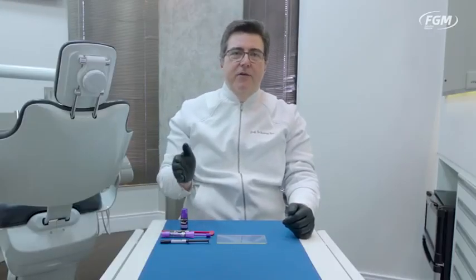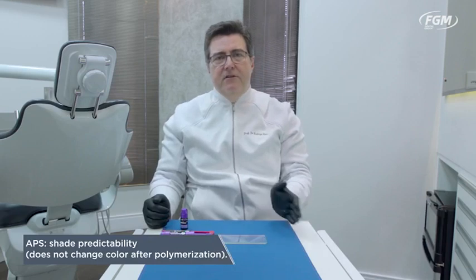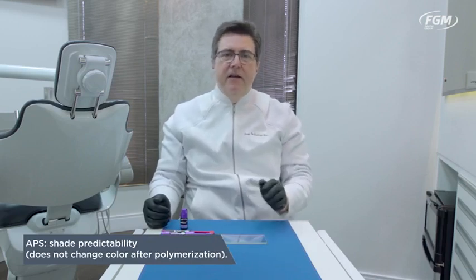After these demonstrations on the composites with APS system and worldwide camphorquinone-based brands, we were able to perceive clearly some key features and advantages. First of all, composites with APS show no color mismatch or difference comparing before light curing and after light curing — this is a clear advantage, giving you more aesthetic predictability on your results. Composites heavily dependent on camphorquinone are yellowish in appearance and have a color shift after light curing, which reduces your predictability on color selection.